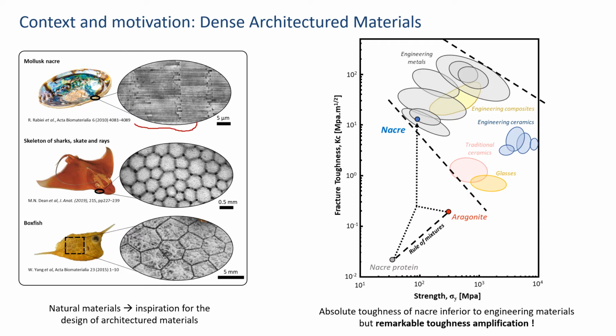So you see that the nacre is made of these little bricks, a few microns length. These bricks are actually made of aragonite, which is very rigid, but also it's some kind of ceramic, but it's also very brittle. And in between these bricks, there is, for example, the nacre protein, which can be seen as a polymer, which is relatively weak, but at the same time it's quite ductile.